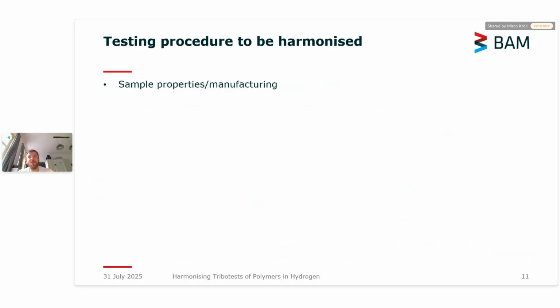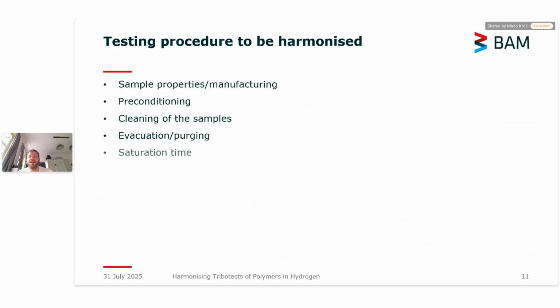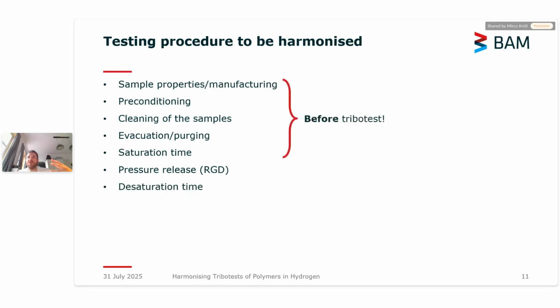If you're talking about harmonization, as I said, the procedure applied will influence the outcome. So we need to harmonize things regarding the sample properties and manufacturing, the preconditioning, the cleaning, how to clean the chamber you want to test by evacuating first or purging, the cycling purging, the saturation time, the pressure release. Some polymers are sensitive to rapid gas decompression, and then the desaturation time. What I want to say with that is you need to harmonize things that happen even before the test and after the test. So it's not just the tribo test, it's also things before and after.